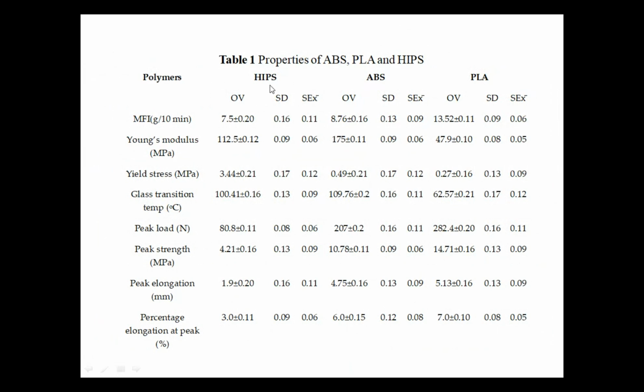Like the HIPS, if I see the MFI of this is 7.5, the melt flow index. I already explained what is MFI, how many grams per 10 minutes this material comes from a standard MFI tester as per ASTM D1238 standard, right? You see for HIPS it was 7.5, for ABS it was 8.7, and for PLA 13.52. That means the flowability of PLA is more. So if I work at the same temperature condition, the PLA will have a better flowability.